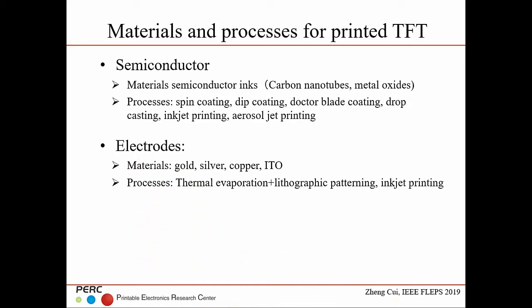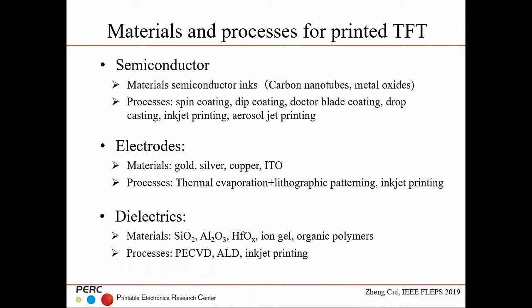For the electrode, we use gold, silver, copper, and ITO, and the technologies to make the electrode include thermal evaporation, lithography patterning, and inkjet printing. For the dielectric, we use simply silicon dioxide, and aluminum oxide and hafnium oxide using ALD, and even organic polymer. The ways to deposit them are either PECVD, ALD, or simple inkjet printing.